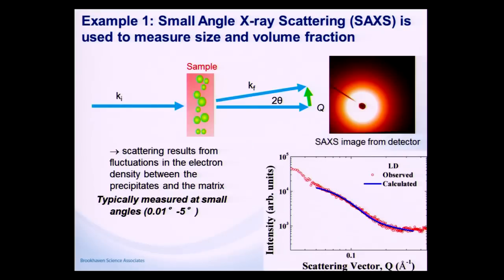This is the first example. We did small angle X-ray scattering at XPD just in April as our first light experiment. So we have an incident X-ray beam. It hits the sample, scatters off the nanoprecipitates, and this is the image that we collect at the detector. So this is the image from the detector. Then we take the integrated intensity from this image and plot it versus the scattering vector and fit a model to it.